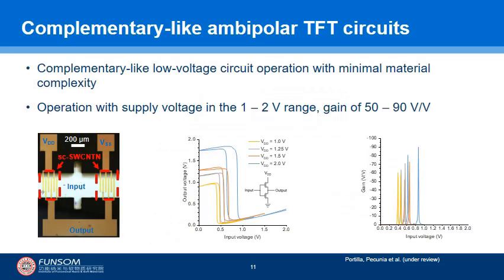By integrating such ambipolar transistors in CMOS-like fashion, as shown in the micrograph, we could obtain, for instance, complementary-like inverters. Their voltage transfer characteristics give a fairly symmetric switching threshold, and their high-to-low transitions cover a large fraction of the rail-to-rail range, especially at low VDD values. For those of you that wonder about the hysteresis that appears in these characteristics, we found that it arises from trapping due to impurities in the CNT ink, an issue that we later solved. These inverters also give a very large voltage gain, up to about 90 for VDD equals 2 volts. All of this provides the first ever demonstration of the viability of ambipolar, complementary-like, low-voltage CNT-TFT electronics through hybrid nanodielectrics.